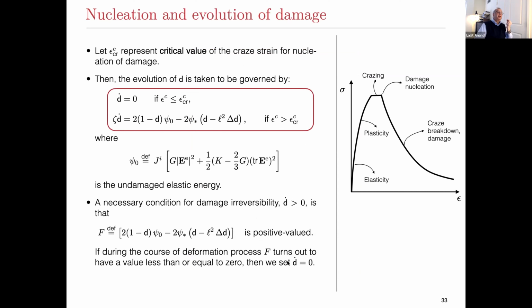Okay, but we need one other ingredient. So this was true when damage is happening, that microforce balance, but when does damage actually start? The theory doesn't tell you that. You have to introduce it as an additional ingredient. And the simplest thing you can think of is when the craze strain reaches a critical value, then damage starts. Then the fibrils sort of say, ouch, I'm done, I'm going to break, and then damage starts. So you introduce a critical craze strain criterion. That means as long as the craze strain is less than some small number, there's no damage, no craze breakdown, but after that, it satisfies that partial differential equation.